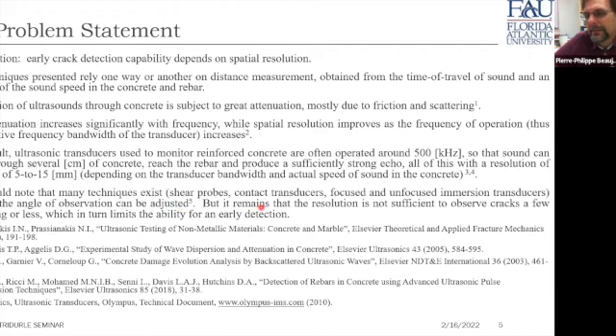But the fact is, it remains that the resolution is not sufficient to observe cracks a few millimeters long or less. That is, if we have a crack which is like a quarter of a millimeter long, these transducers will not be able to create an image of sufficient resolution to depict it. So that in turn limits the ability for an early detection. So early detection is actually limited by the physics of acoustics and the physics of transducer operation.